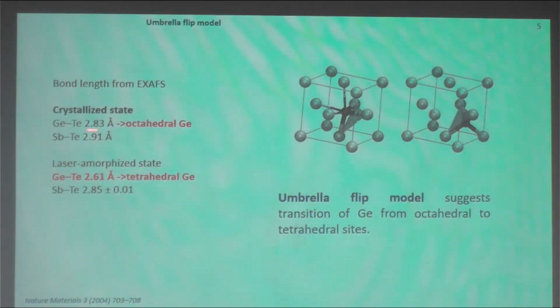They also studied the crystallized state, and here there are also two types of bonds, germanium telluride and antimony telluride. They are a little bit different, but not so much. If you look at the environment of this germanium and antimony, we know that they sit in octahedral sites in the crystalline phase. But this bond length suggested that the germanium is sitting in tetrahedral sites. And so in 2004, Kolobov and Tominaga proposed the so-called umbrella flip model.